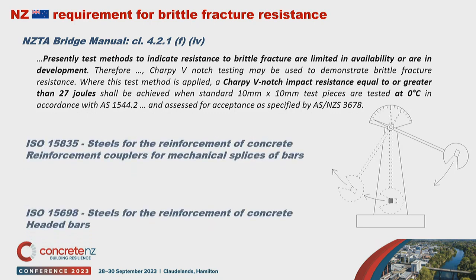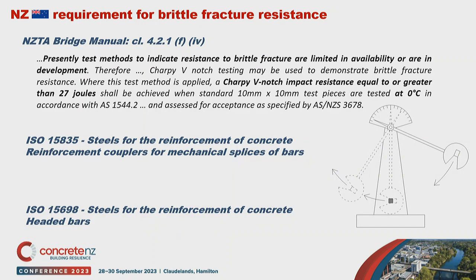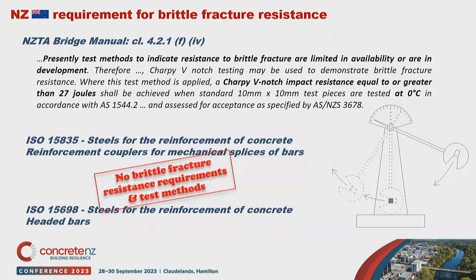So having said that, we've looked at other international standards, which are also cited by 3101 and the Bridge Manual. The first one is ISO 15835, which is a specific standard for reinforcement couplers, and is cited by both the Bridge Manual and 3101. And also ISO 15698, which is a standard specific to headed anchors of reinforcement, which is only cited by the Bridge Manual, not by 3101. But both of them have no requirement or comment about brittle fracture resistance and test methods for that. It almost looks like it's not an issue.